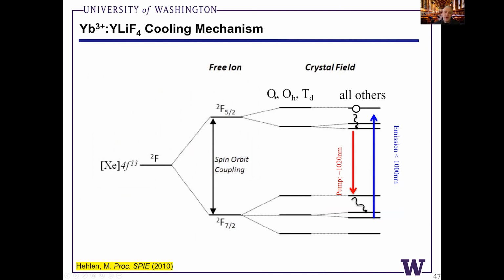So if you have high symmetry, octahedral or tetrahedral point groups, you get a triple level, which has a degenerate middle state below a double energy scheme with a degenerate lower state. But in this ceramic, we have a lower symmetry S4 point group. So all of the f orbitals become non-degenerate. You have 4 levels under 3. So what we're doing is pumping at 1020.